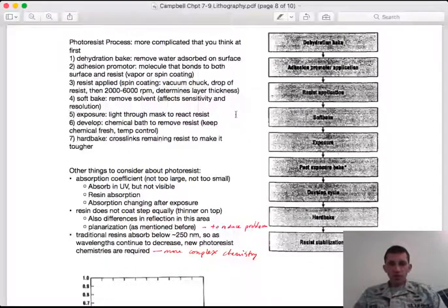So you put it in a vacuum chuck, you spin it up, you deposit a drop of photoresist, and that is immediately spun out to a very thin, very uniform layer. The amount that you apply doesn't necessarily dictate the layer thickness. That's driven by the spin rate. And if you apply too much, it's just going to spin off and coat the walls of the inside of your spin coater, which is common. That's kind of how you know you have enough.